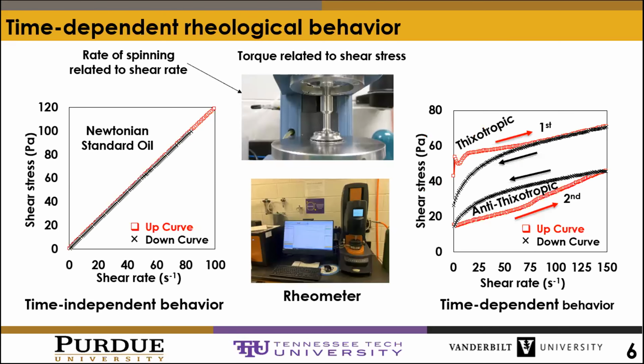So now let's discuss rheology even further. One way to study the flow of cement paste is through rotational rheometry, where a small thin film of material is placed between two parallel plates, and one of the plates is spun, usually the upper one. And when you do that, you generate a flow curve, the plot of shear stress against shear rate. And for a Newtonian fluid, regardless of whether one is increasing or decreasing that spinning rate, that fluid behaves exactly the same along a straight line. The shear stress depends only on the shear rate.